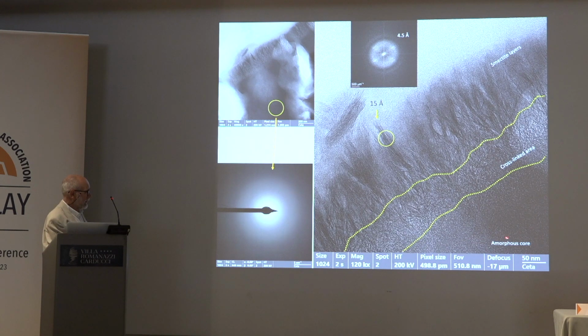What can you measure in here in terms of high resolution? Almost anything. Then evolve to intermediate band with this here. You see here the different aspect. It's a cross-link area. We couldn't identify any lattice ring in this area, but it's the place where the plates grow. It really resembles some plants growing from the soil, no? And the smectite layers in this crystal, we made an FFT image. We have two points, 4.5, and also the spacing is 15.